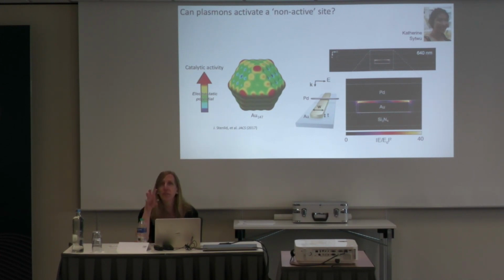Oh, so they don't need to be spherically symmetric. And in fact, you can have, say, nanorod geometries. And there you have two different resonances. So the color you'll see will be dependent upon either the polarization of light or if they're all aligned. Or you could just illuminate with a filter, right? If you have sunlight and then you put a red filter in or a green filter in, that might correspond to, say, the longitudinal resonance or the transverse resonance.